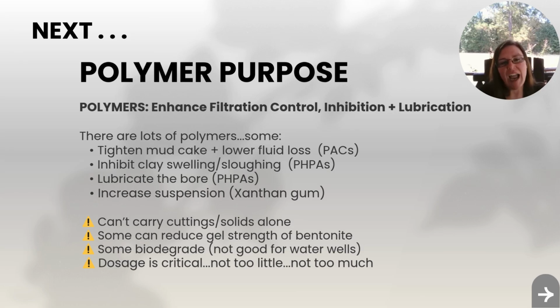So when we provide the naturally occurring bacteria all around us with a food source, that bacteria keeps growing and growing and growing, and it now becomes a problem. If you've ever held onto a fluid or had to use a fluid for a long period of time and you put a natural polymer in it, like xanthan, you might notice it starts to smell, like it starts to smell rotten.